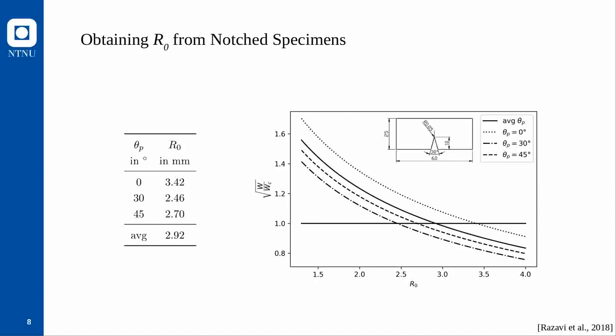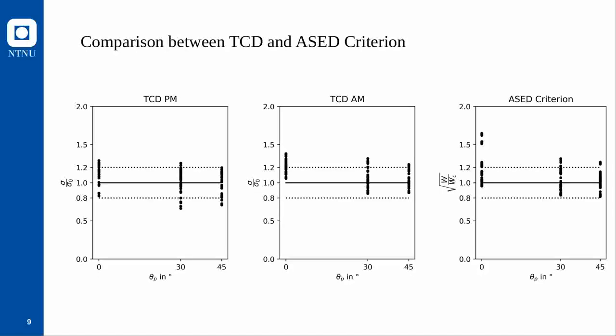When using this calibrated approach to obtain R0, the accuracy of the ASED criterion is almost identical to that of the TCD point method and area method. The scatter is almost entirely within the ±20% scatter band, with no scatter exceeding that band on the non-conservative side — unlike the point method but consistent with the area method. However, there are some significant outliers on the conservative side.